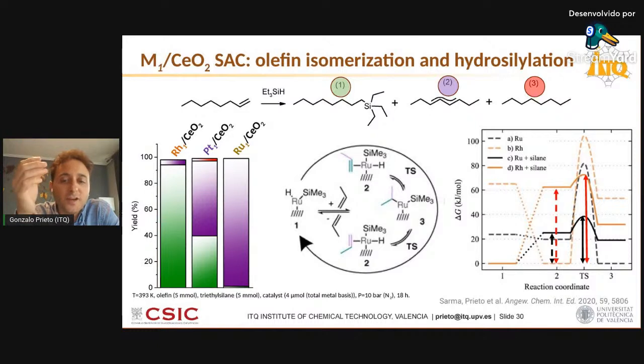And the reason for that was tracked to the quite high difference in energy barriers, above 35 kilojoules per mole difference for the rate determining step of olefin isomerization, double bond migration. That barrier, as I show with the full arrows on the plot, is dominated by the adsorption energy of the olefin on different centers, ruthenium or rhodium, which is what I show by the dashed arrows on the plot.